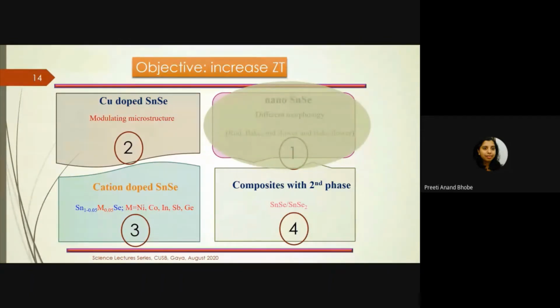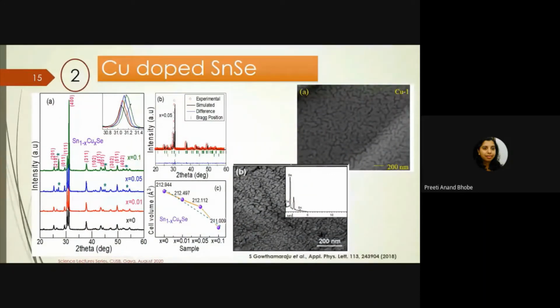So what happens when one tries to put copper in SnSe? What we realized is that you cannot put a lot of copper in it. We put 1%, 5%, okay. But the moment you increase from 5% and try to go higher, then you start getting some secondary phases, or copper forms some different compounds with selenium, and so it comes out as a secondary phase. Whether it is good or bad is another thing, but it's not helping us to achieve the aim of putting copper in SnSe. It only tells us that only up to 5% copper you can put without actually disturbing the crystal structure of SnSe. If you try to put more copper, it will try to come out of the system and form its own secondary phase.